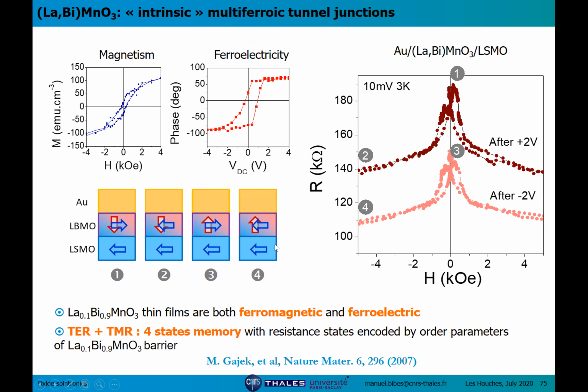And there we had the combination of spin filtering leading to the TMR effect and ferroelectricity leading to electroresistance, which is shown here by the shift between these two TMR curves. So we have basically 4 resistance states that are encoded by the magnetization and polarization in the multiferroic barrier. Okay.